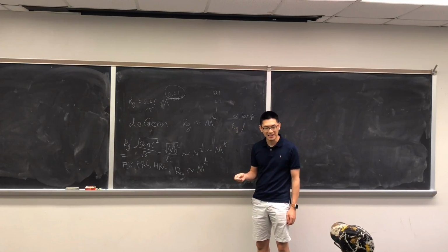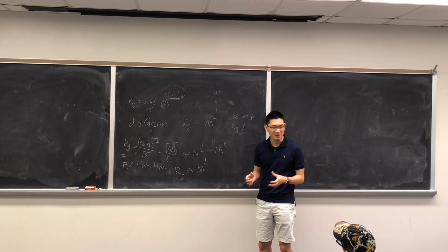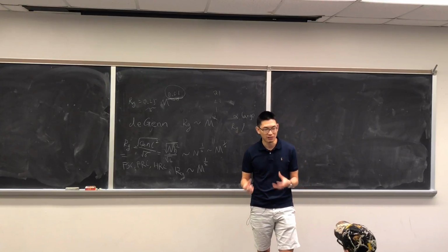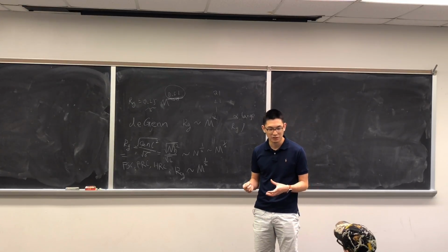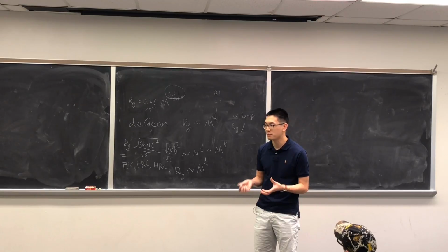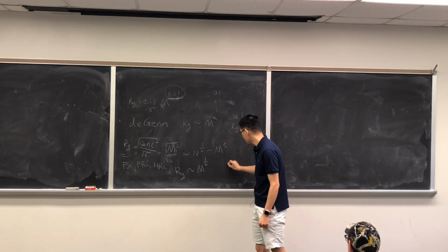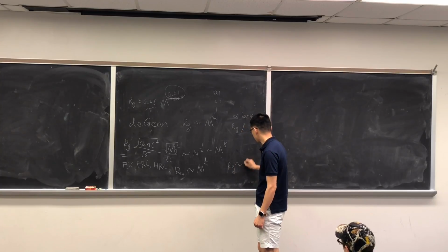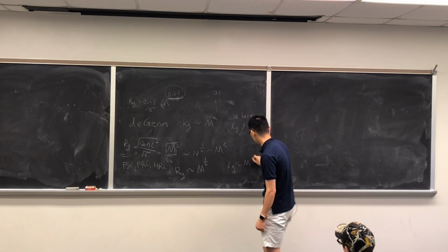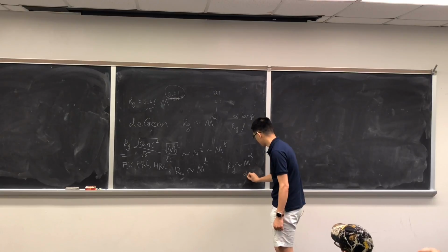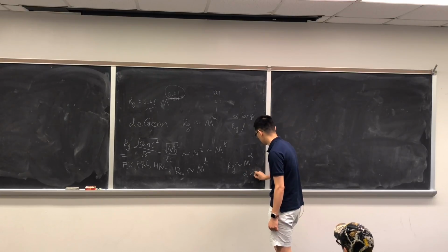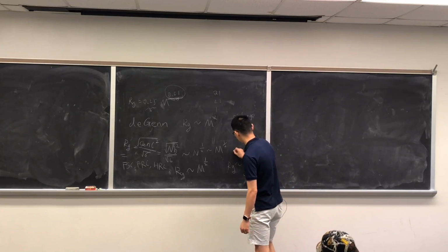Those are two special cases, but in a real solvent, you have to consider self-avoiding walk. It means your chain cannot occupy the same space twice. So as you can imagine, Rg is proportional to n to the alpha, but alpha will be larger than 0.5 for sure for a good solvent.